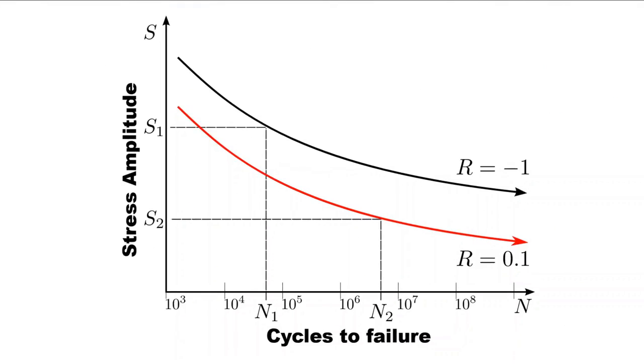As I mentioned earlier, there are some conditions that are more aggressive and can lead to fatigue occurring earlier. Here are two non-ferrous SN curves. The top is for a fully reversed condition, as indicated by the load ratio R. This means that the curve was found from testing where each cycle had a mean stress of 0, or the tensile stress was equal to the compressive. Below this is the result from a different load ratio of 0.1. This scenario has the material experiencing a non-zero mean stress, or the material is under more tension than compression at any given point in time.